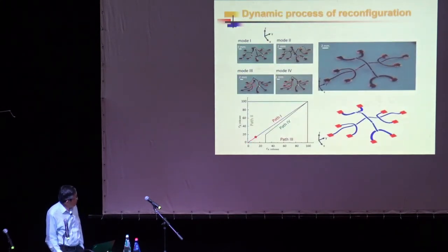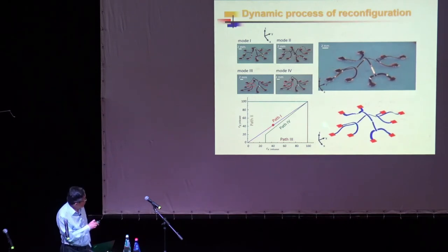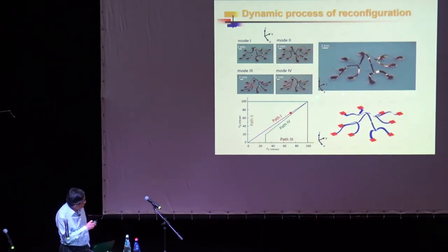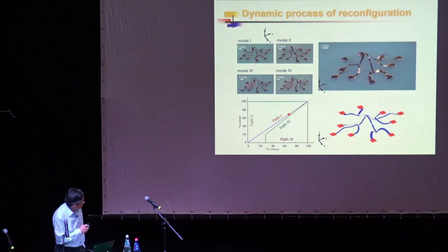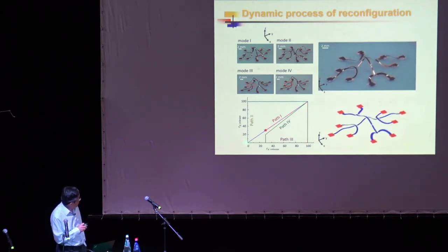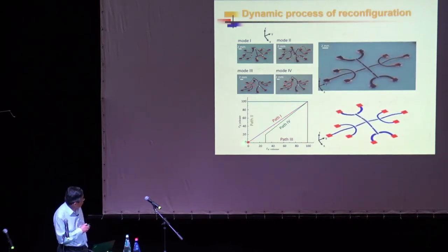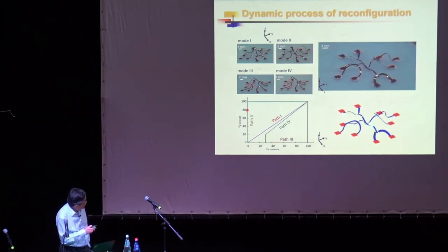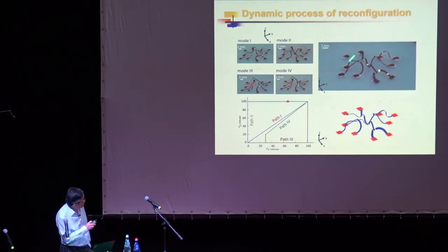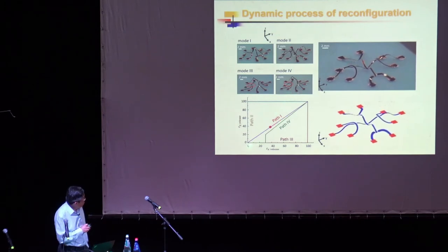In fact, the shape is not just two. It can be much more. For example, the theory and the experiment released simultaneously, you get one shape we call mode one. This is shape one. That's released simultaneously. But now if you release them sequentially, you can choose to release in the Y direction first. You can see Y is relaxed. X is still being held. Now X is relaxed here. Again, theory and experiment. You can see here that you reach this shape. We call it mode 2.